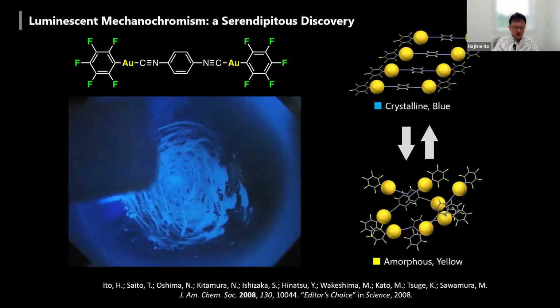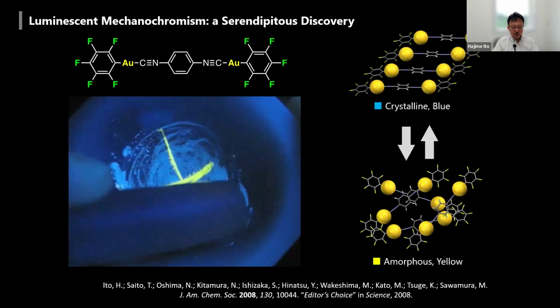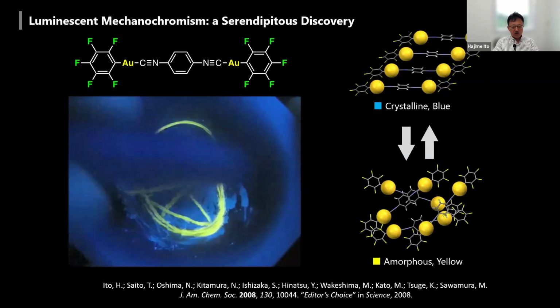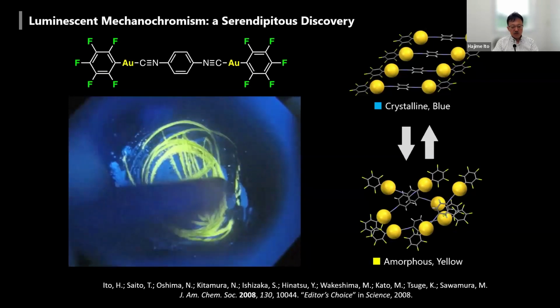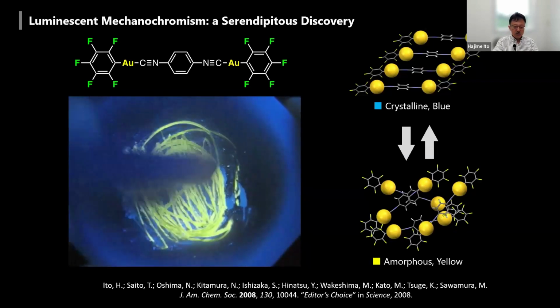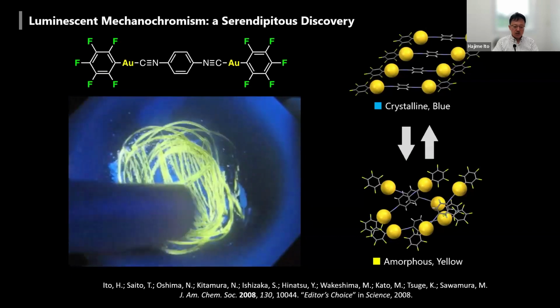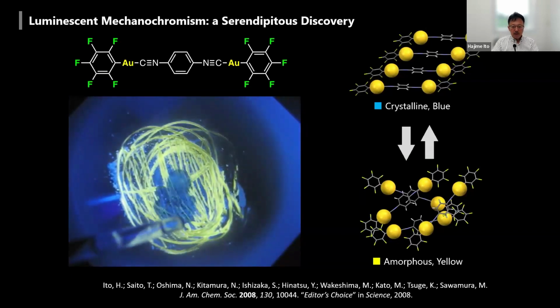After the evaporation of solvent, you can see this color change again and again without any color degradation. We checked this at least 20 times. We can repeat this blue-to-yellow, yellow-to-blue change like this.